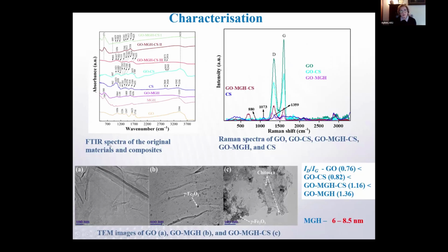FTIR spectra indicated functional groups available for adsorption, and Raman spectra again showed a very high oxidation level of graphene oxides, and this is important for synthesis of nanocomposites. TEM images showed the morphology of these samples. You can see particles on the graphene sheets, sample B, and also small particles of 6 to 8 nanometers can be seen in the samples.